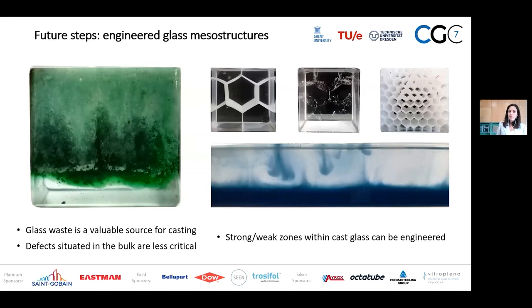But more importantly, if you start thinking that the defects in the bulk are not that critical anymore, then we can start envisioning composite glasses, where you can have a strong pure zone only when it's really required, and we can fill up the rest of the space with a glass of a lower grade, the one that actually no one wants. And we could also envision a different way, really engineering inside of our glasses weaker zones in terms of crystalline interfaces or even subtle bubble veils in a way that we can have a very predictable failure.